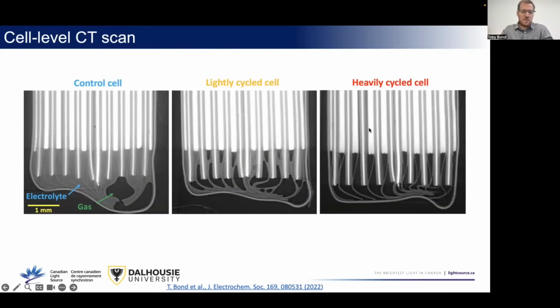And if there's not enough electrolyte to go around, then you start to have certain regions that are actually going to be dried out. And this is another thing that could cause rollover failure, because you have this kind of critical point where you start to run out of electrolyte, and then the lithium ions can't move through it as easily anymore. So these things are all linked together, and they're all a result of microcracking.